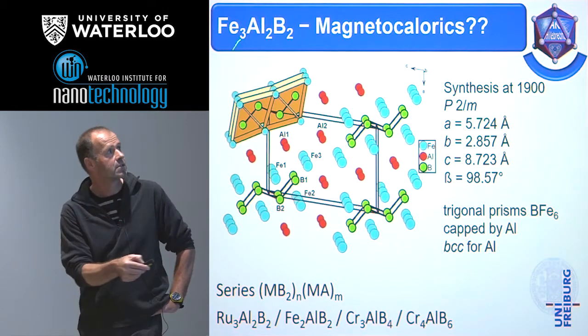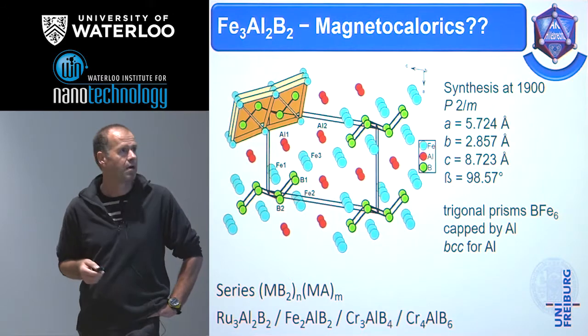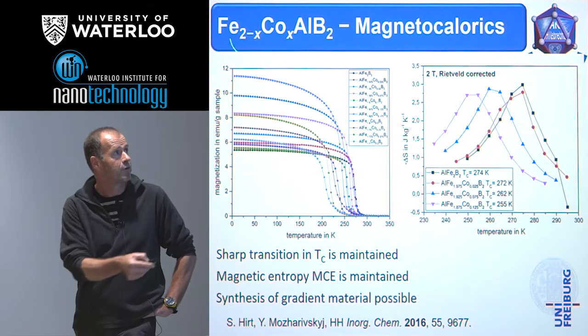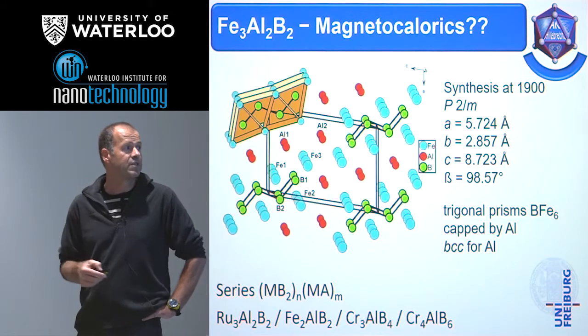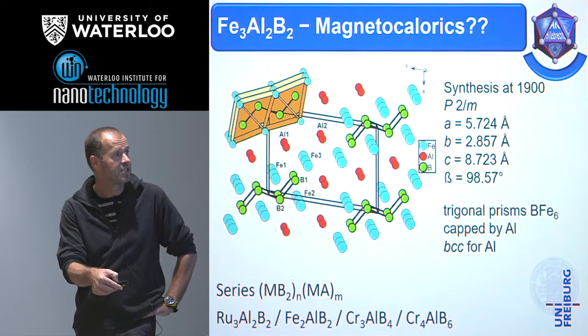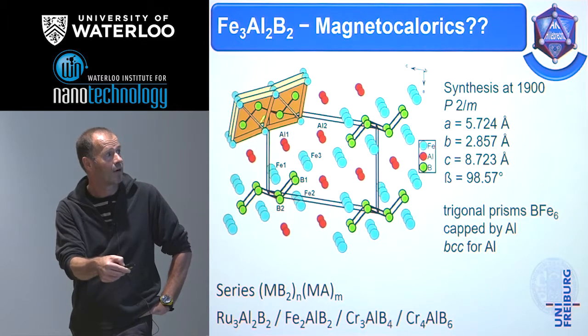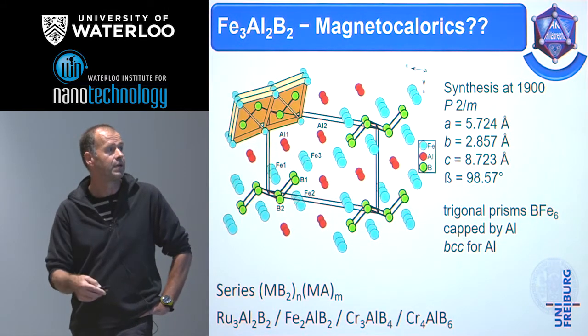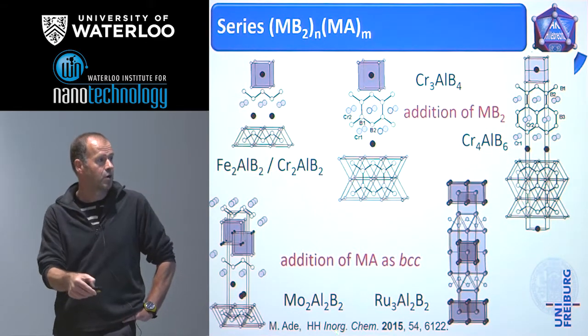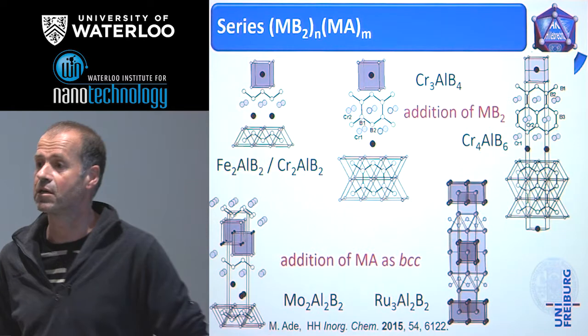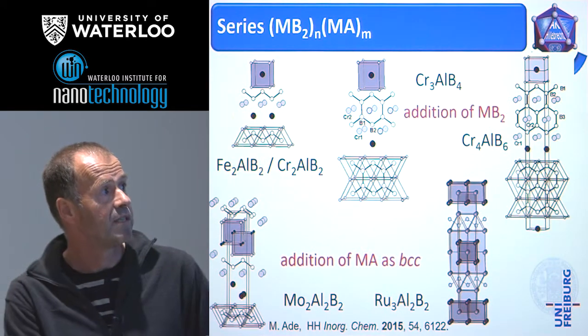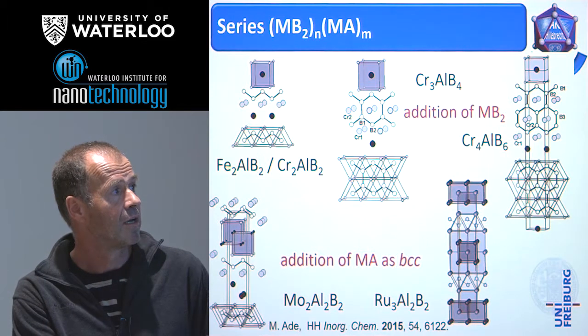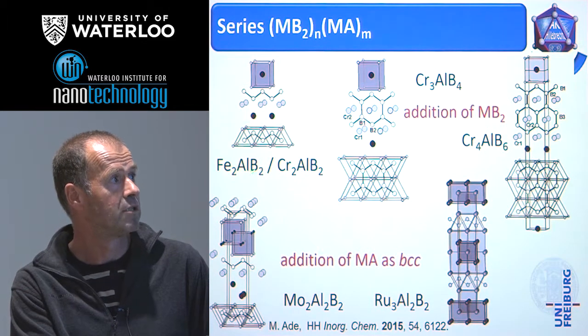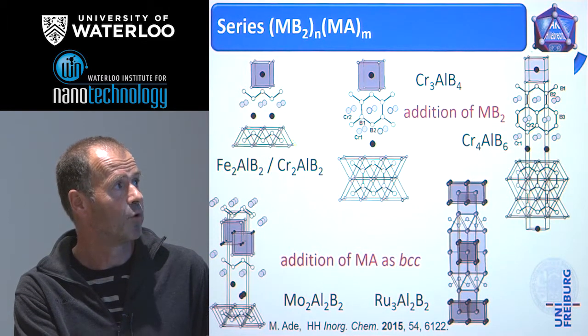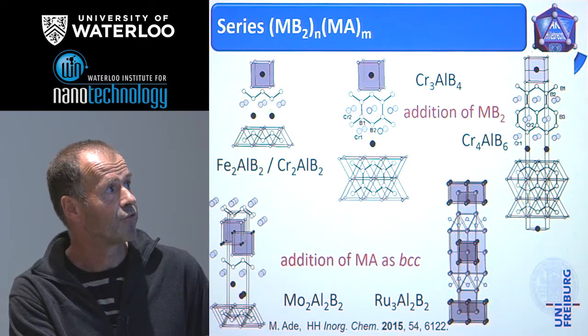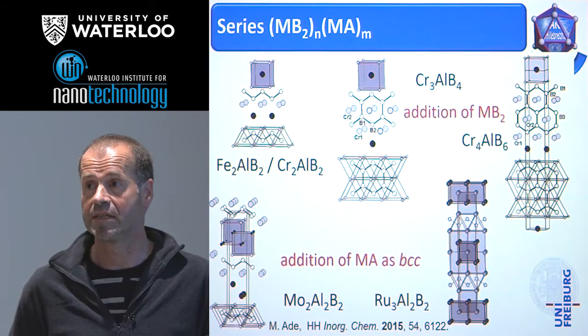Now we could show that this composition is a quite simple structure derived from our first material here, because we see there's a complete series of these materials where we have the transition metal boride part and an intermetallic boride part. And some years ago we had a nice work on systematic variation of these ternary borides. You may see here our first example with a composition 1, 2, 1, 2 with zigzag chains of the boron and the metals in between, and this is a fragment of a cubic body-centered packing.